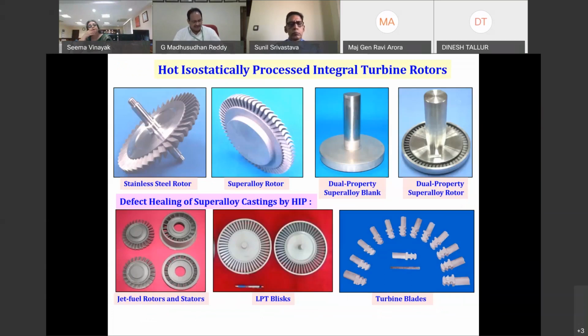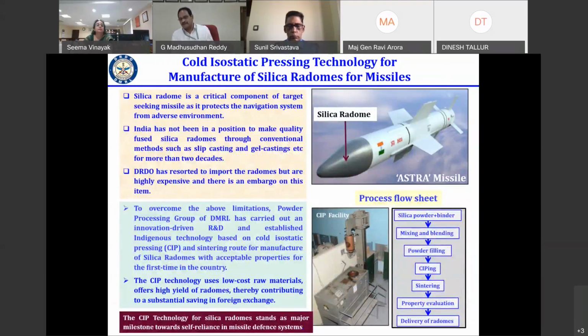DMRL has a lot of expertise in using powders to produce components of dual property superalloy blanks, and we're also using sintering technology to heal the defects for various aeronautical applications. Since we have metallic powders and a lot of expertise, we ventured into another activity: can we make radomes with ceramic powders? Presently, they're producing radomes with silica using the slip casting route. The yield is quite low, and the radome is the most important part of a missile, which protects the navigation system of a missile from adverse environment without affecting the electromagnetic performance of the antenna.